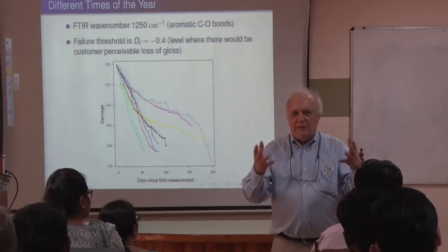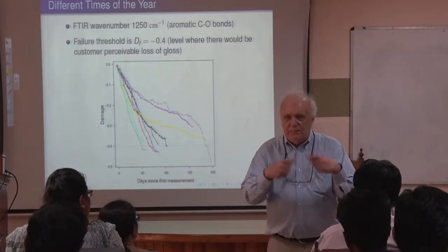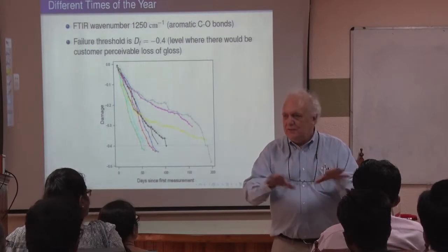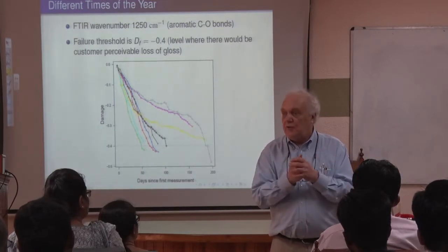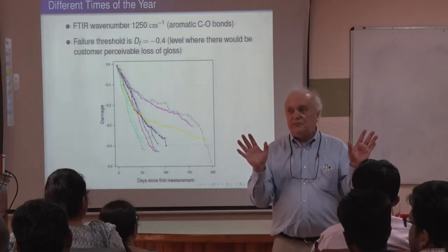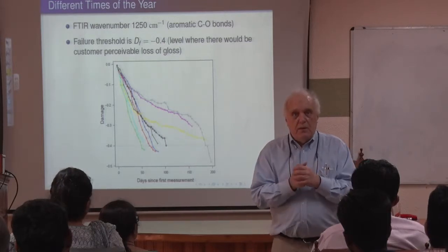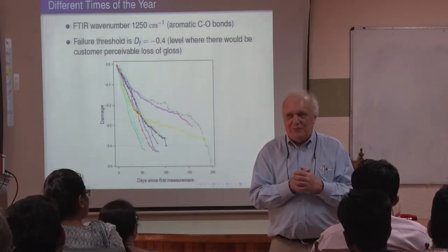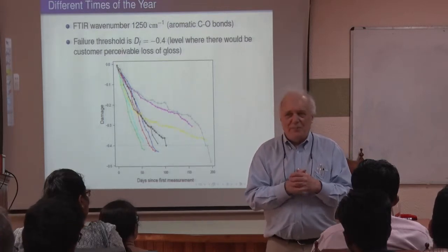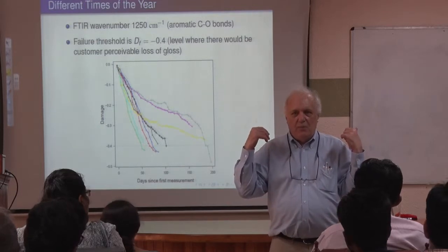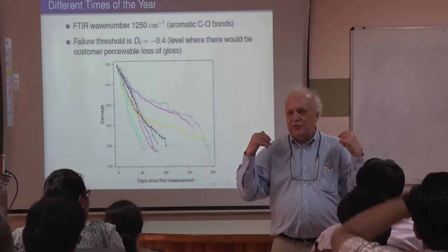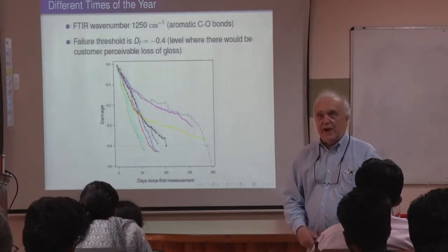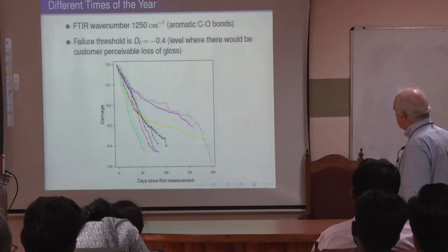And when you have a paint and a coating, you can mix something like, it's the same chemical, you can mix that into the coating and it will protect it from the sunlight. It will last long. It's very expensive to use it, but these specimens did not have that because we wanted to get results quickly. Otherwise, instead of months, they might have to wait years to see an important amount of damage. So that's kind of another accelerating factor that was being used here.